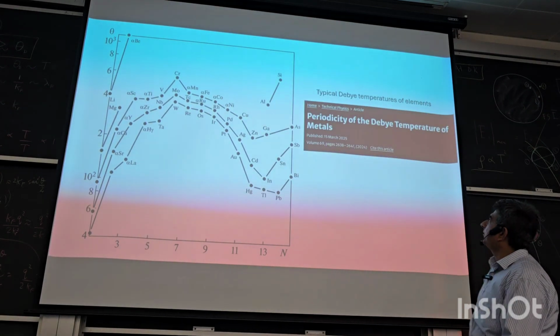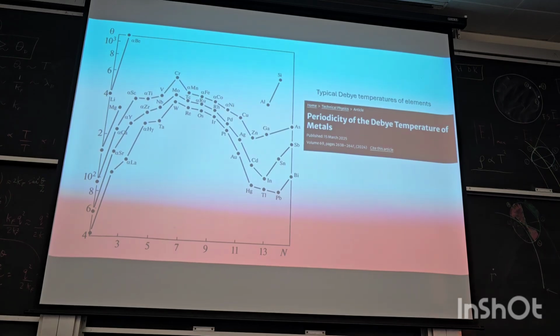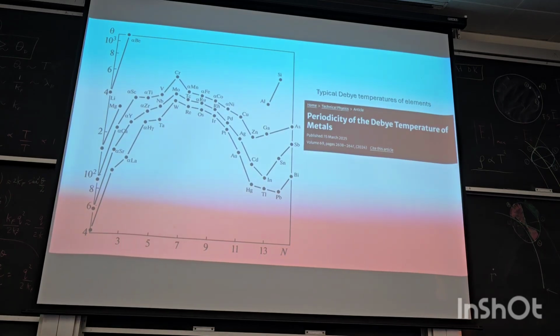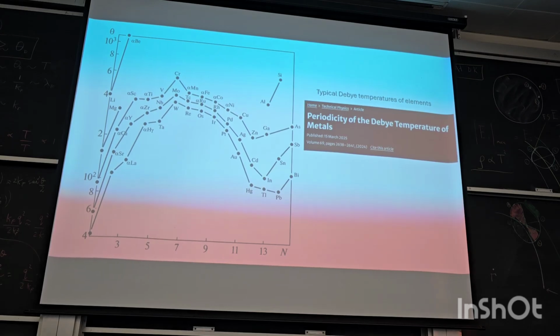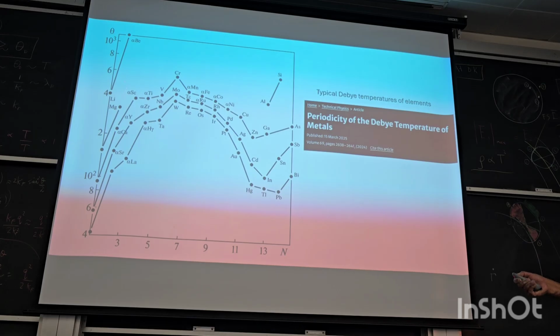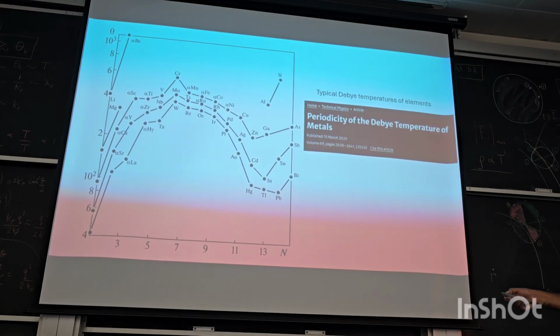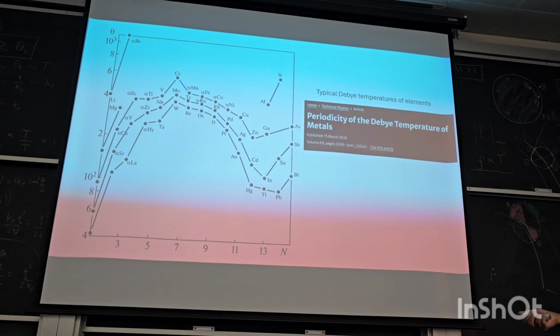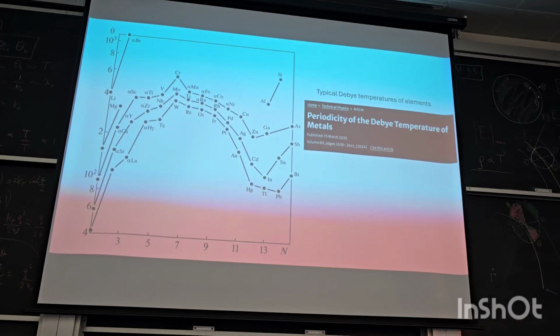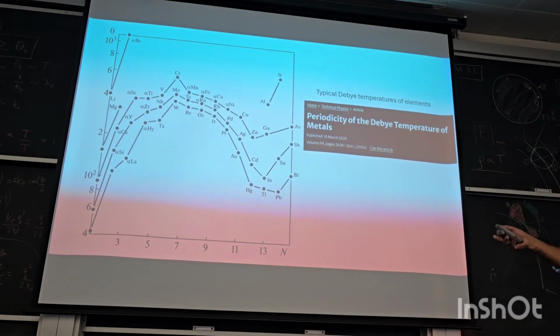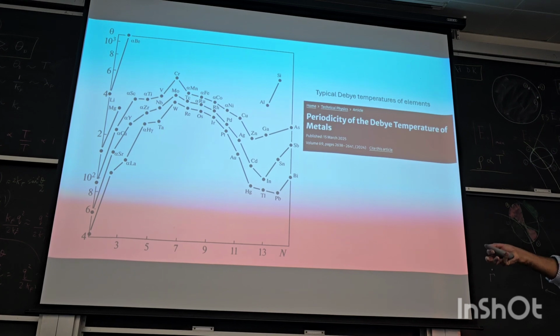And if I were to show you the Debye temperatures for these solids, theta D, the Debye temperatures for these metals are roughly between 100 Kelvin and 700, 800 Kelvin or 1000 Kelvin. So all of the Debye temperatures are within this range, of the order of room temperature. And that was my original claim when I was building the argument for what's happening at high temperature.